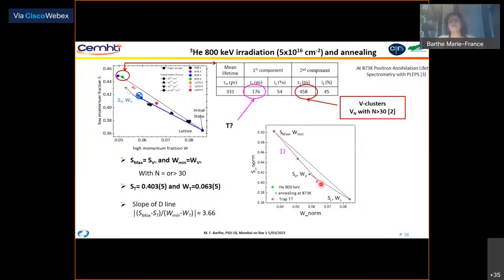This star has been plotted using the intensity of these two lifetime decomposition, and we obtain the values of S and W for this defect T, with a slope of this magenta line corresponding to annihilation competition between this state and T1, which is 3.66. And we think that this point corresponds to annihilation in vacancy clusters, large vacancy clusters, with a number n of vacancies larger than 30.